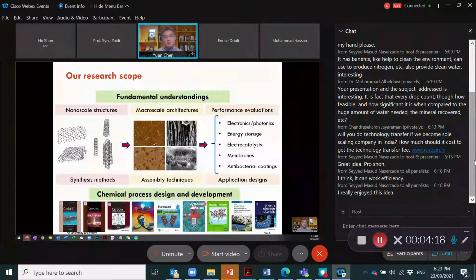The reason, in my view, is that there are two issues which have to be addressed to really push those materials into more applications, like the hydrophobic membrane already mentioned. The first one is nanoscale structure control. Carbon nanomaterials are different from traditional carbon because their nanoscale structures are unique. However, for most synthesis methods, it's not easy to control the nanoscale structure. For example, pristine graphene is highly hydrophobic, but once you oxidize it, it becomes hydrophilic. So how to precisely control the surface functional groups to get the desirable property hasn't been solved. So precise, scalable nanoscale structure control is the first issue to be addressed.